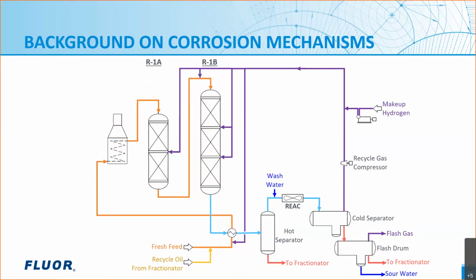This affects the corrosion in the REAC because now you don't have the beneficial effects of having some liquid hydrocarbon there, which act like a coating on the metal surfaces, because the corrosion is occurring primarily where water is in contact with the metal surfaces. So now that it's only vapor, the corrosion mechanisms have a higher risk of occurring. And it makes the water washing a bit more complicated and so on.